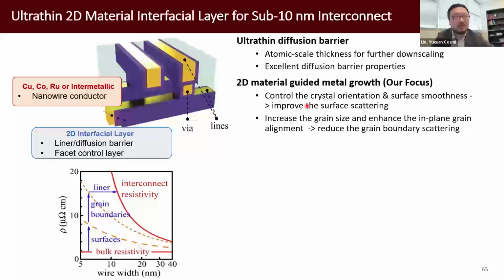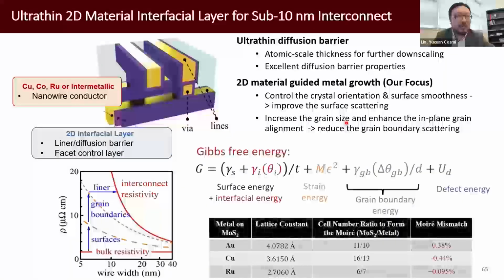Our focus is to use the same structure, but we can use the 2D material as a template to guide the metal growth. And so we can understand this system by this Gibbs free energy. There are terms related to surface or interface energy, strain energy, grain boundary energy, if there are grain boundaries, and also defect energy. So with 2D materials, we can engineer this interfacial energy.